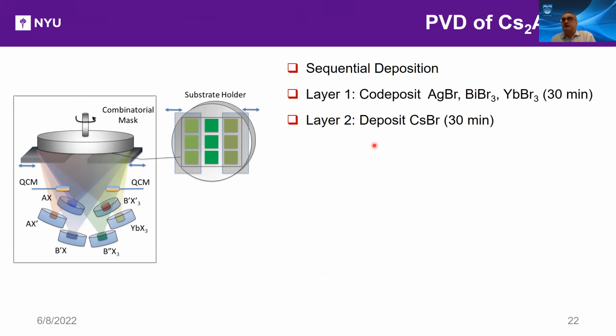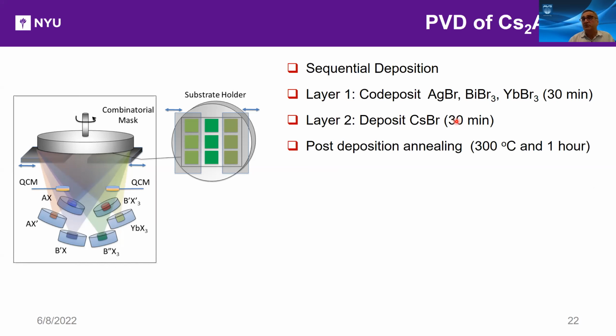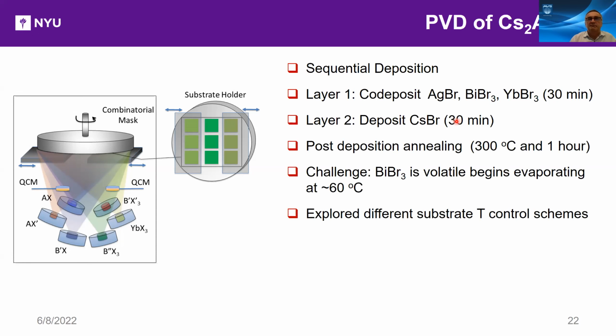So some specifics about how we do the deposition. We do sequential deposition in the following way. We deposit the first layer, co-deposit silver bromide, bismuth bromide, and ytterbium bromide. And then we deposit a cesium bromide layer each 30 minutes. So it is layered. And then we anneal that film at 300 degrees centigrade for 1 hour. Using combinatorial methods, we vary the temperature and the time, and this happens to be the optimum for reasons I will tell in a minute.